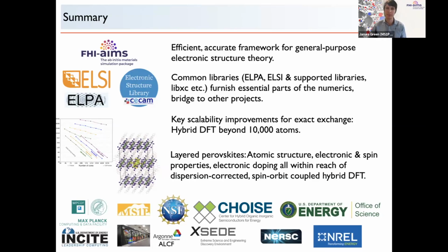How does the choice of inorganic cation influence the electronic properties and stability of layered hybrid perovskites? So in the inorganic cation, it depends on which cation, right? So the inorganic cation is on the B side. So for example, the lead will shift around the actual band gap, for instance, if you go from lead to tin or from lead to something else, that changes. It will also affect the stability in that example, because tin is more easily oxidizable, and so the material becomes less stable in air. That's the case for tin. And so in many respects, changing the cation, of course, has the appropriate chemical responses, but you want to test them and you want to know about them, and they're all individual.